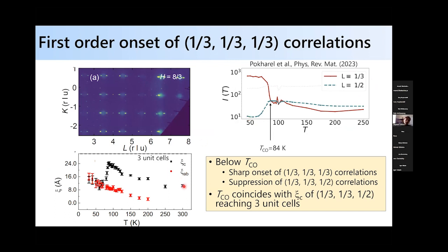Moreover, you can look at the correlation length. If you look at the correlation length of these third a half correlations along the c-axis, you can see they more or less remain flat. They start diverging, you hit around 3 unit cells of correlation along the c-axis, and then, boom, the onset of long-range charge order at the third a third type position occurs.